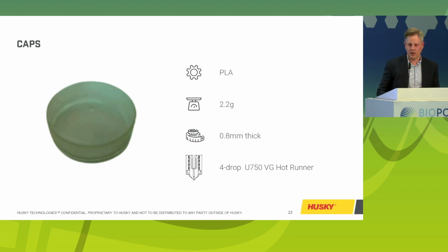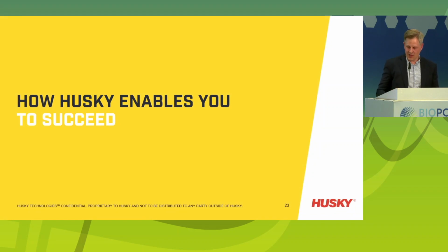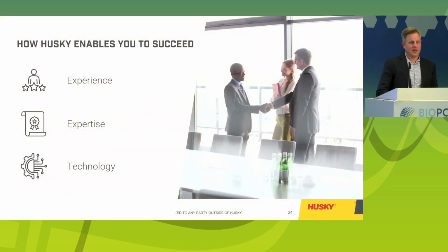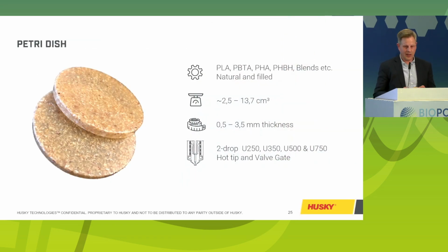Not all products I can show here, so that's why I go to the next slide and tell you more about how Husky can enable you to succeed. We have the experience, the expertise, and the technology. Like I said, we have a global team. The global team has access to mold flow, FEA, CFD, and as well the resin test lab. The resin test lab, I have here as well with me a few examples. We have a Petri dish, which is flexible between 0.5 of a millimeter wall thickness up to 3.5. It's a 2-drop system, and we can run it in different kinds of hot runner versions, from the smallest nozzle to almost the biggest series we have, as well as hot tip or valve-gated solution.